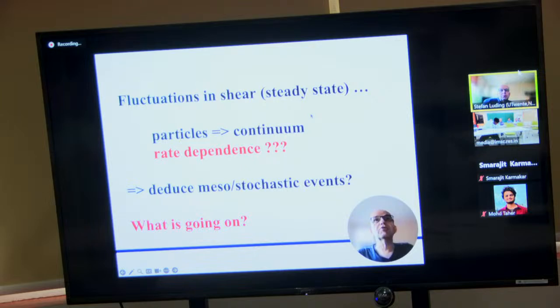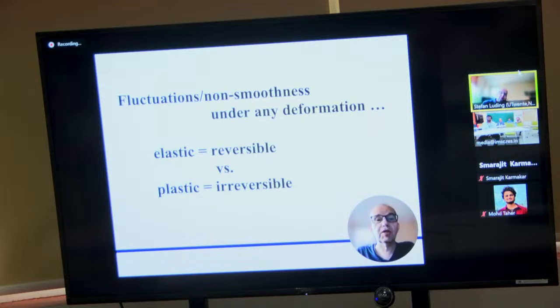Okay, so this is the statistics about the fluctuations. This is continuum. I did not yet bring in the rate dependence, and I introduced the probability for events, so elastic behavior and plastic stress drop events. So what is going on? The evolution of stress, the fluctuations which you saw, the statistics, under any type of deformation. I only showed you shear so far. Under any type of deformations, there are two possibilities: elastic, and that's what I call reversible events, elastic stress changes, they will be reversible by definition, and plastic, and they will be irreversible.